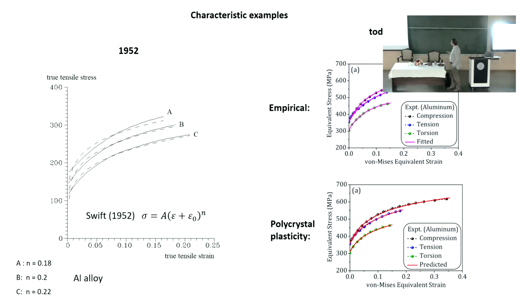In 1952, we are with Swift. This is the function we try to fit on the material, so the fitting is the broken line, and A, B, C are three different tensile test curves on an aluminum alloy. The fit is there but not fully, there are deviations of course.